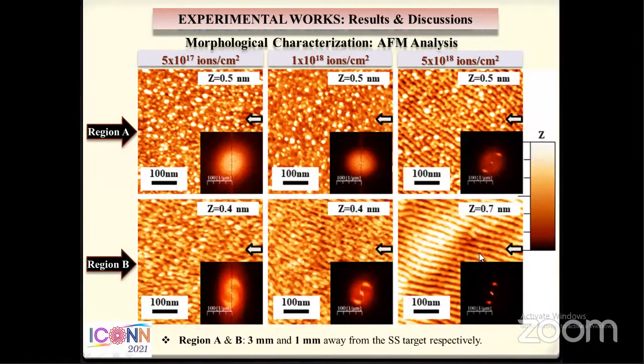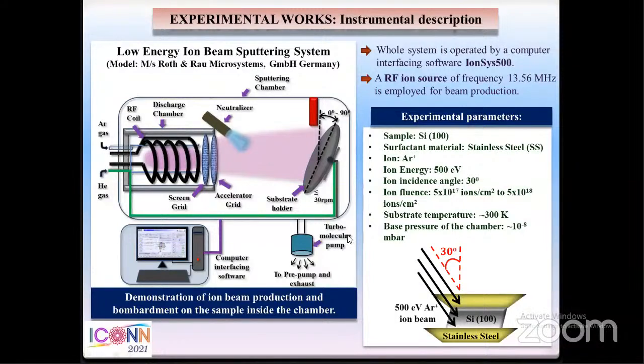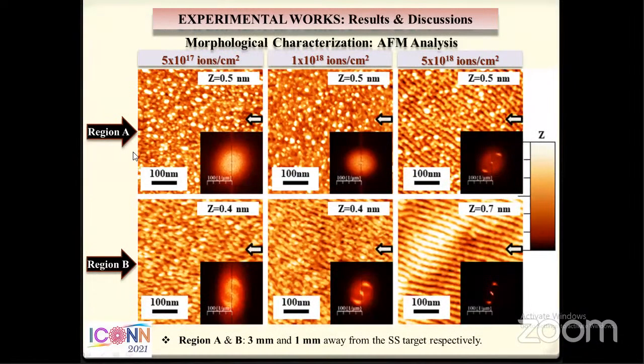So these are the morphological analysis of my sample. Actually, I have done the morphological investigation at 2 different regions. That is, here you can see one near the surfactant material and other far away from the surfactant material. So the region that is far away from the surfactant material, that is region A, is 3 millimeter away from the stainless steel target material. Here we observed that with an increase in ion fluence, some nanodots split over the surface. And for the highest ion fluence, it is observed that there is a transition from nanodot to nano ripple like